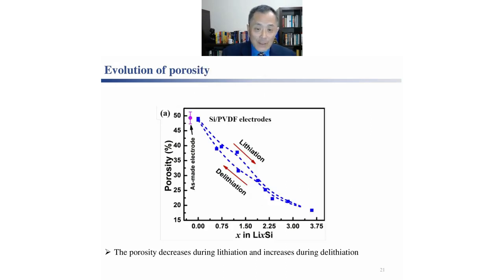We measured the porosity of the electrode and found that as we lithiate, as lithium enters into the electrode, the porosity decreases. This is because during electrochemical cycling of the battery cell, the electrode is constrained by the cell casing. Therefore, as the silicon expands, the electrode porosity will decrease because the total thickness cannot change to accommodate all the volume change of the silicon particles. So the porosity decreases during lithiation and then increases during delithiation.